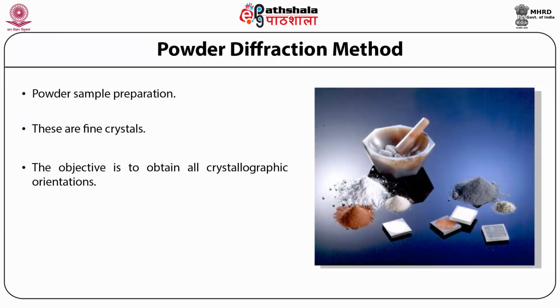In slide 15, you can see the typical samples or powders which are used for powder diffraction patterns. You can have a little mortar and just grind your samples here. Grinding means you are breaking them into fine crystallites. They are still crystallites. Any powder which you see is of the order of some hundreds of microns in grain size, but they are all crystallites, and you paste them on a slide and make the measurement.